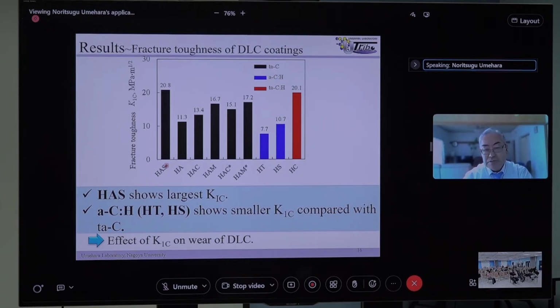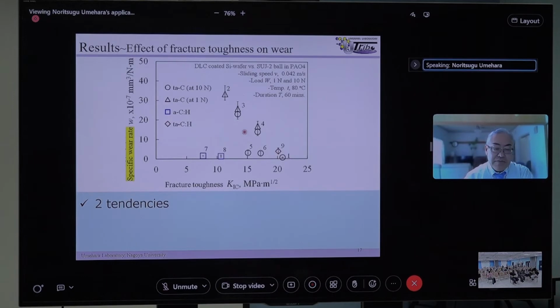ta-C shows the minimum wear, and it shows the maximum fracture toughness. That is so nice. The other hydrogen-free DLC has quite large fracture toughness, and the hydrogenated one is slightly smaller. But if we rearrange the relation between the specific wear rate and the fracture toughness, we can see two tendencies.